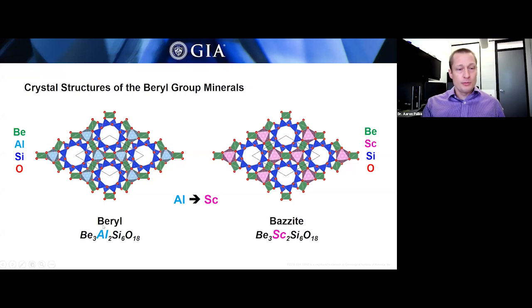Beryl is beryllium, aluminum, silicon, and oxygen. And you see the aluminum occupying that octahedral site in the beryl structure in that light blue octahedron. To make bazzite, you would substitute scandium for all that aluminum in the structure. Now on the right, you see bazzite with scandium in that pink octahedral site. And that's what's making these two different minerals with the same overall atomic arrangement of their atoms within that mineral group.